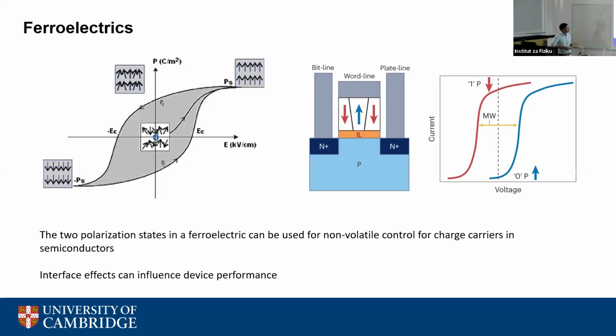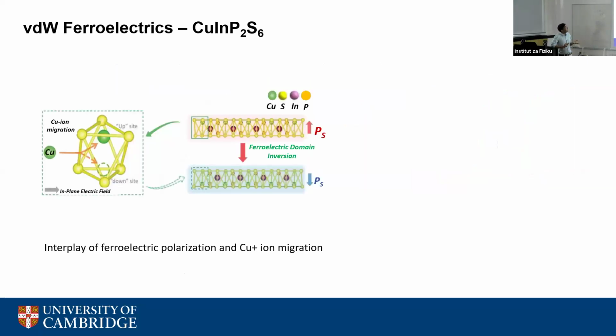But we wanted to study what happens when you put ferroelectrics and semiconductors together, when you have van der Waals ferroelectrics. This is a very classic van der Waals ferroelectric. It's called copper indium thiophosphate. It sounds very complicated, but basically it is a sulfur octahedra where you have copper ions, and the two polarization states in the ferroelectric are attained when you can electrically switch the copper from the upside to the downside in the lattice. Now, the copper ion here is quite mobile. It's like an ionic semiconductor, which makes it very interesting because you can switch the ferroelectricity with field, but you can also make the copper ion move around.